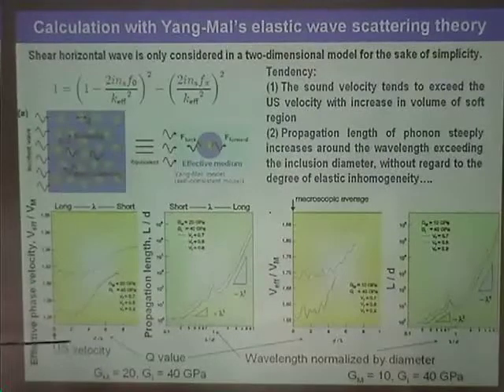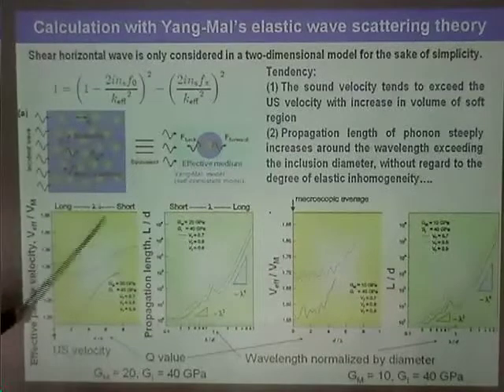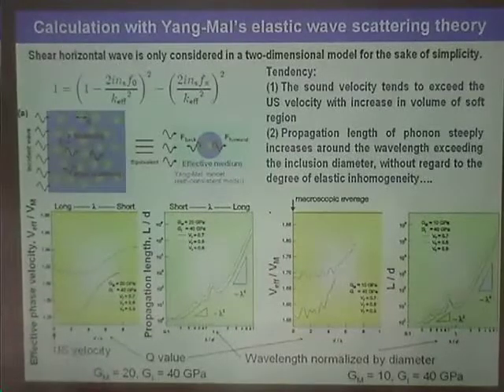Okay, so the length scale is not the same in the experiment. No, the model. In the model there's only one length scale, the diameter of that object. So this is normalized by the diameter, and everything is related to that length scale. The lengths aren't exactly the same. On the right, the crossover length is maybe 1, and on the left it's maybe inverse 4 or something. So there is a difference, but it could be consistent with a single length scale. Even the model doesn't say that what you calculate is exactly the same. Anyway. Okay.